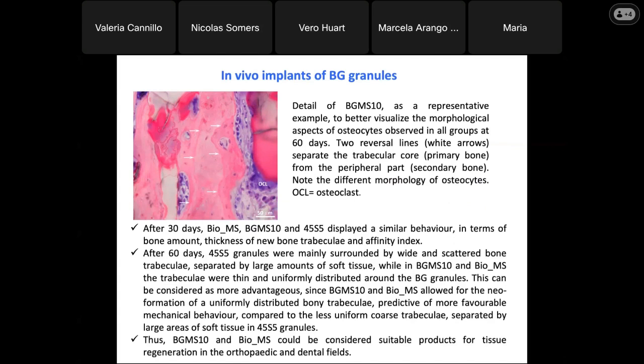And it was interesting to observe that after 30 days, so after 1 month, all the bioactive glasses, including 45S5, displayed a similar behavior in terms of bone amount, bone thickness, thickness of new bone trabeculae, and affinity index. However, after 60 days, 45S5 granules were mainly surrounded by wide and scattered bone trabeculae, separated by a large amount of soft tissue. On the other hand, in BGMS10 and BioMS, the trabeculae were thin and uniformly distributed around the granules,